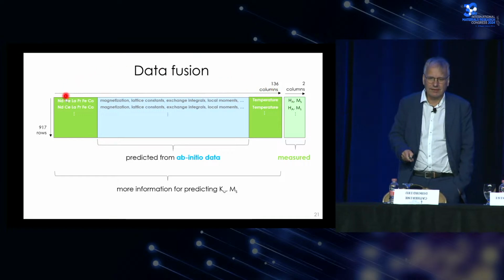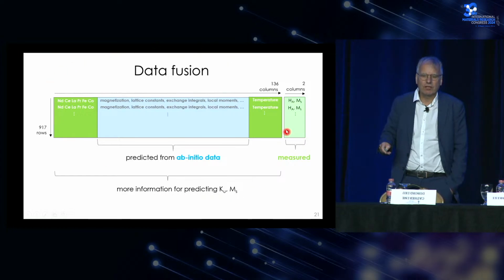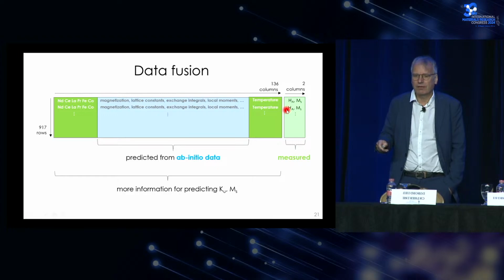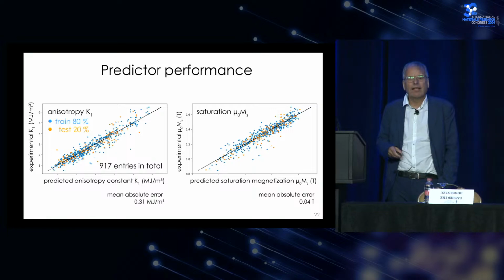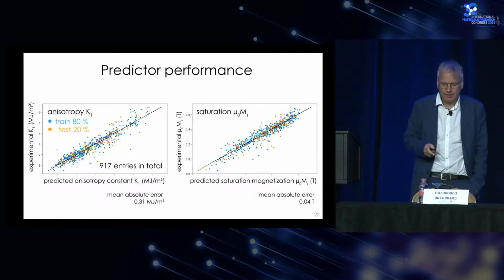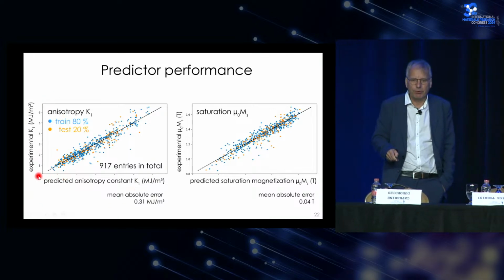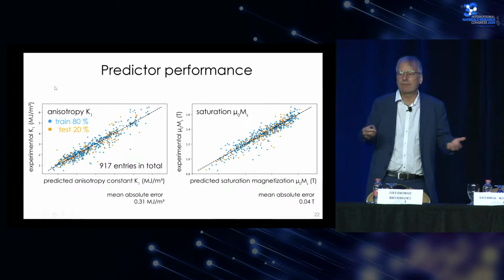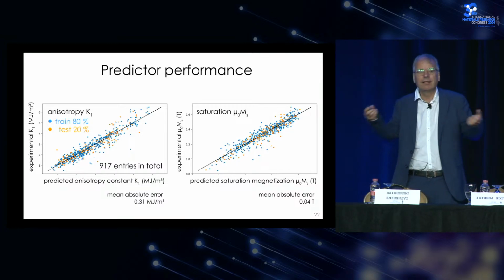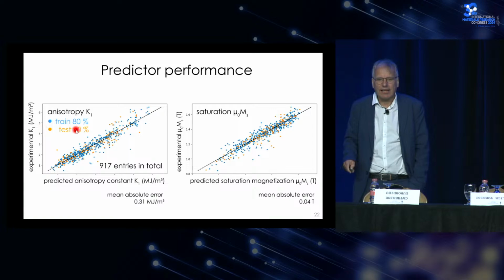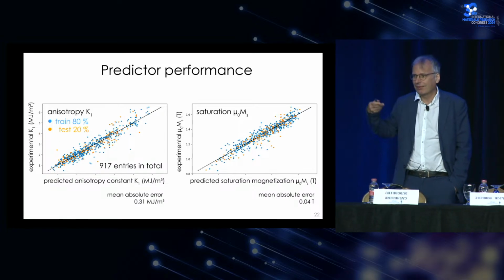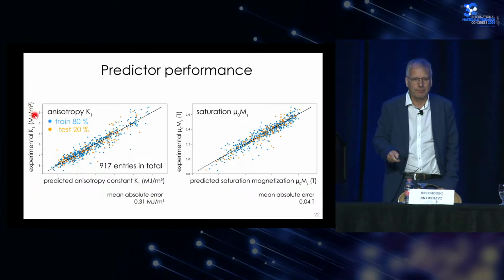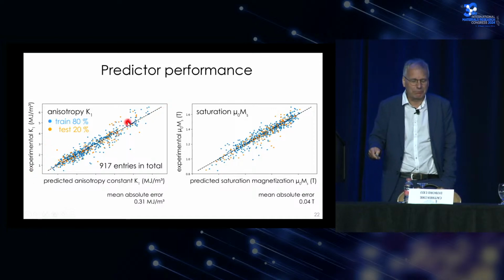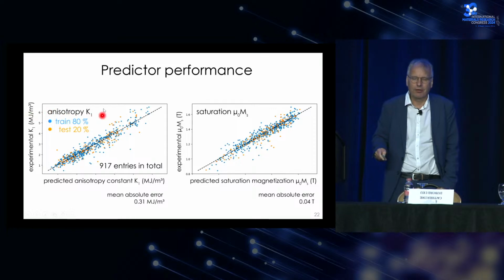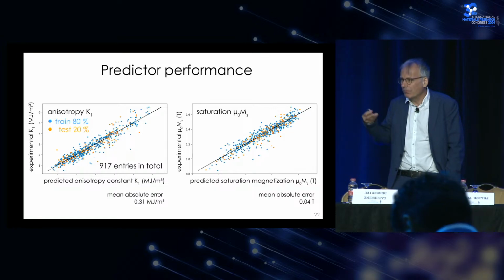There's a lot of data that could be provided by the simulations. We use all this data that you see on the left-hand block in a machine learning model to predict anisotropy and magnetization. Here you can see how this machine learning predictor performs. What we plot here, for example, on this side is the predicted anisotropy constant versus the experimentally measured anisotropy constant. If you do this machine learning, you always make a kind of a test. So you put away a fraction of your data, the so-called test set, and then you check on the test set how well your predictor will predict the anisotropy constant, for example. And you see that the prediction is quite the same on the test set as well as on the training data that was used to train the machine learning model.